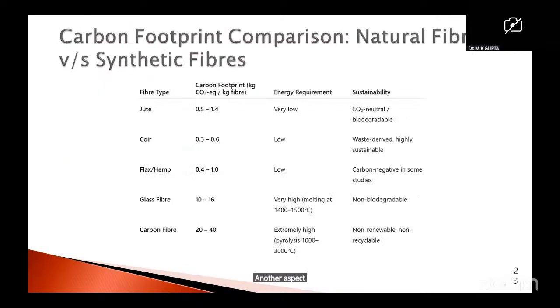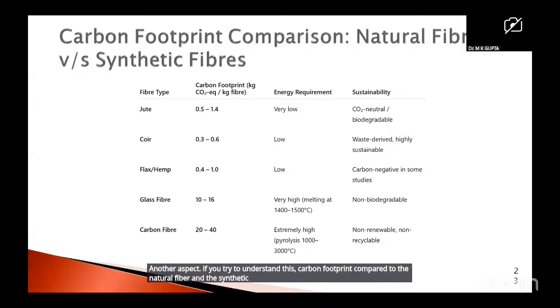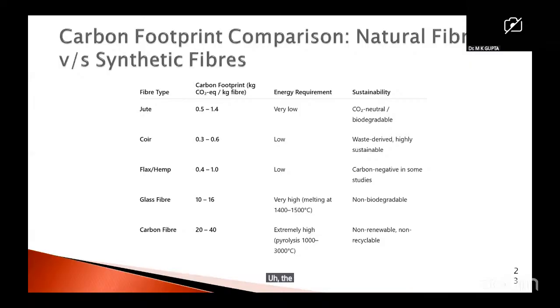Another aspect, if you try to understand this, a carbon footprint compared to the natural fiber and the synthetic fiber, if you see the carbon footprint of the natural fiber is very low as compared to the synthetic fibers. If you see the jute, the carbon footprint for the jute is 0.5 to 1.4. On the other side, glass has 10 to 16. And for the carbon fiber, its values increase from 20 to 40. This table also shows that natural fibers are better for the environment as compared to the synthetic fibers.